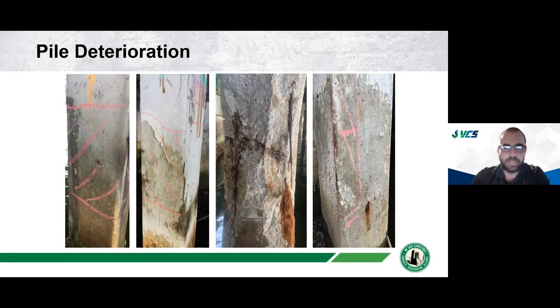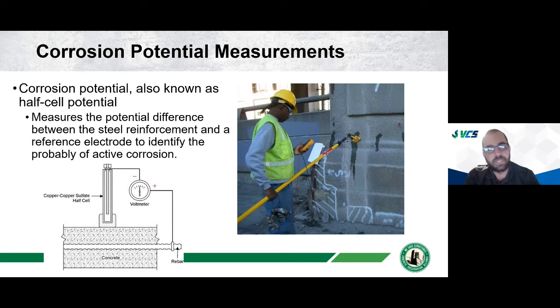So on this structure, we did something called the corrosion potential survey. As I mentioned earlier, this, also known as the half cell, will identify where active corrosion is in reinforced concrete. What we do is take a reference electrode and measure the potential of the reference electrode versus the steel. That potential will tell us the probability that the steel is actively corroding. First we want to mark out where the delaminated concrete is, but then we go down with the corrosion potential survey and identify where beyond the delaminated concrete is corrosion active. We want to know where those delaminations are going to grow to in the next 4 or 5 years. And that'll help us plan proper repair strategies.